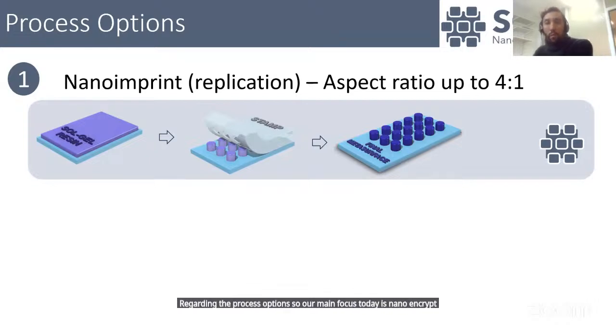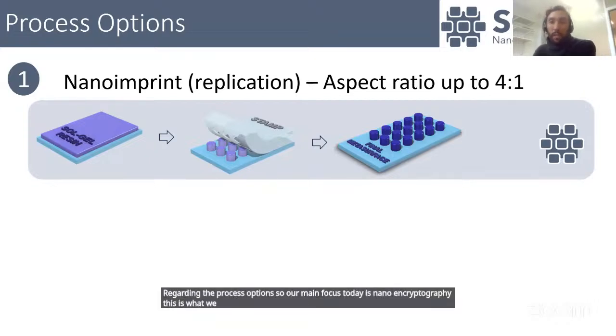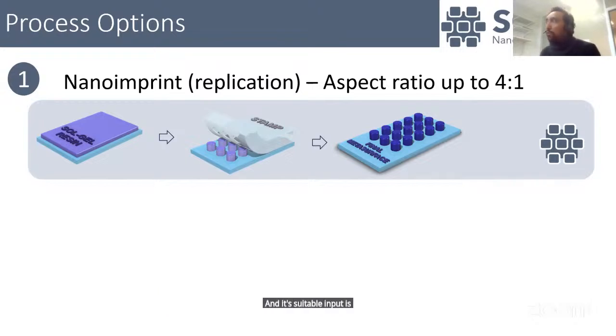This is what we developed for augmented reality applications, where you need to make these slanted gratings or binary gratings, like you all showed earlier. And direct nanoimprint is suitable for aspect ratio up to 4:1. When you go to more challenging aspect ratio,